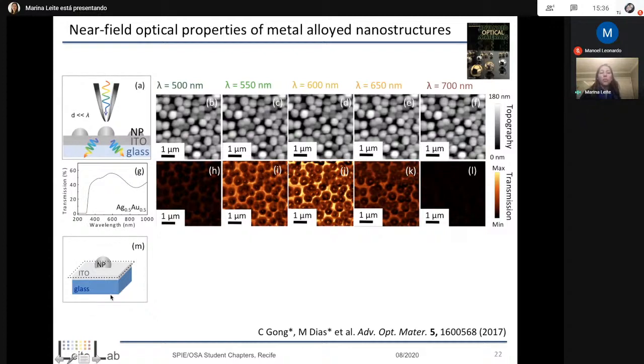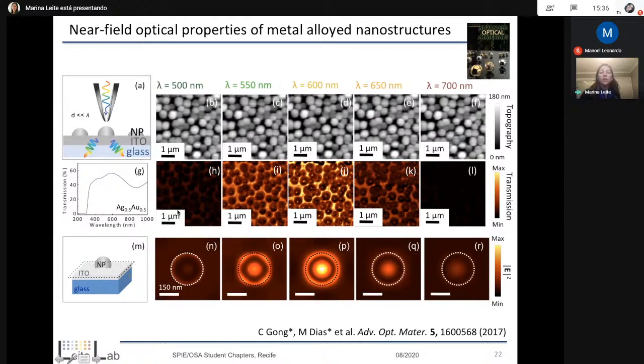So in this case, for example, to represent the light near field, we use a dipole for that. And basically what you're seeing is a comparison between the experiments and the simulation for one particle only, just due to simulation time. We could definitely have made an array, but you can do periodic boundary and just pretend you're repeating that infinitely. And essentially what I like about this simulation is that you can see that at 550, we start observing this quadrupole signature, these four brighter spots. And then once we add resonance, it really looks a lot brighter.